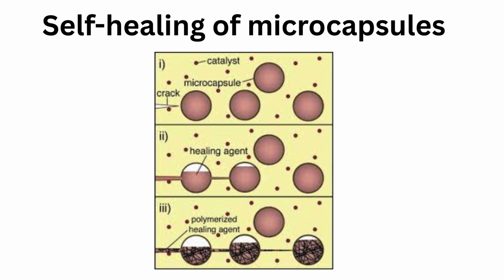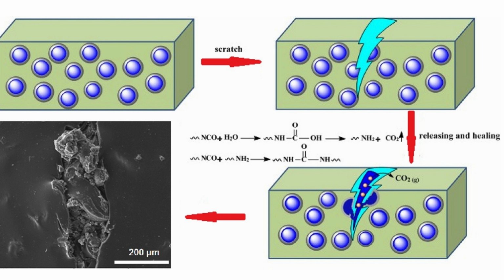polymer network. The research prospect of microencapsulated self-healing is promising, primarily due to its straightforward repair method and notably high repair efficiency. However, a compatibility issue has been identified between the microcapsules and the substrate, with the embedding of microcapsules having a detrimental effect on the substrate's original structure, consequently altering the material's mechanical properties.